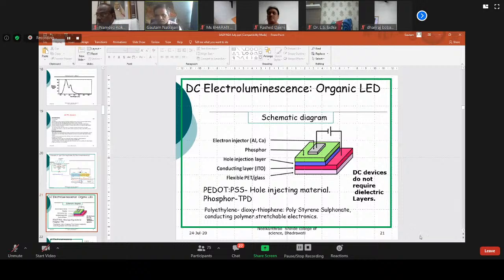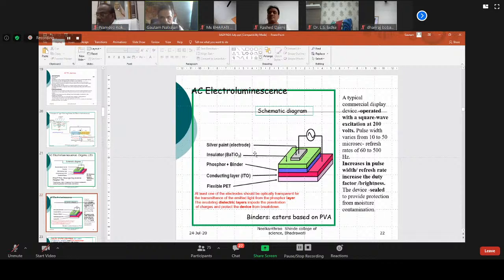Go to next one. AC electroluminescence. Same thing in another diagram. The phosphor binder is ester based, polyvinyl. Just a general example: a typical commercial display device is operated with square wave excitation at 200 volts. Pulse width varies from 10 to 50 microseconds. Refreshing rates are 60 to 500 hertz. Increase in pulse width increases the duty factor and brightness. The device is sealed to protect from moisture and contamination.